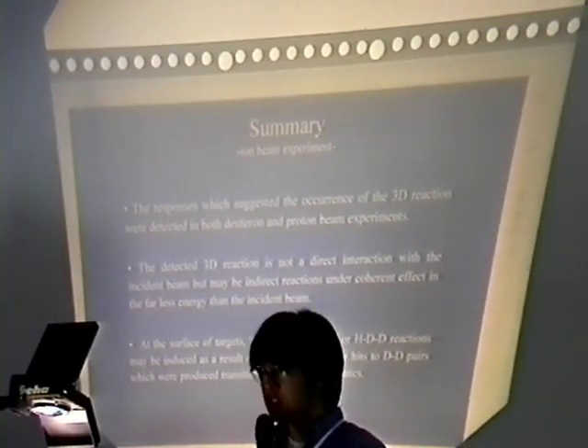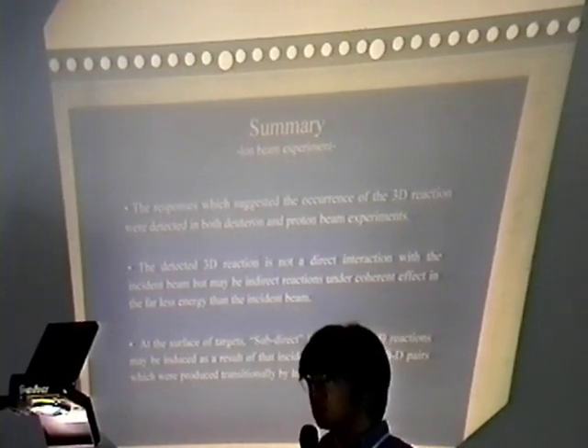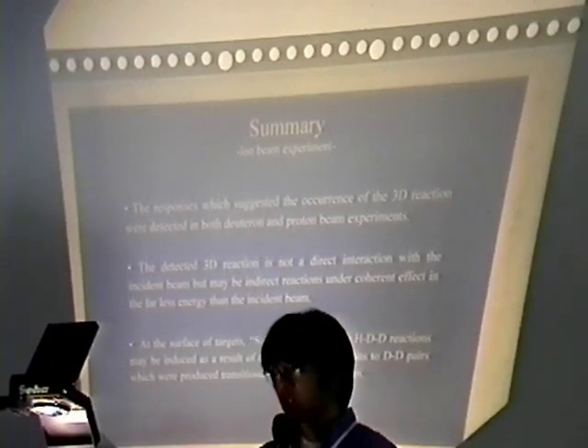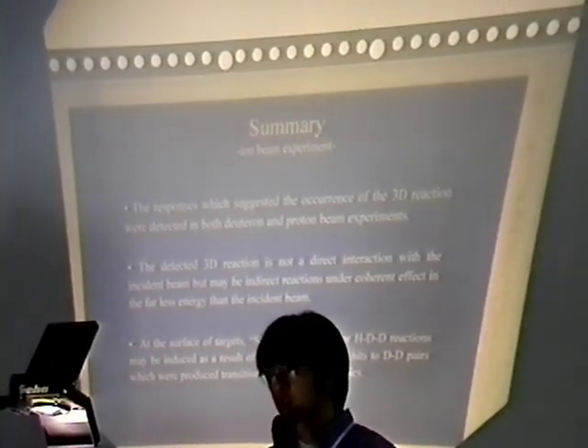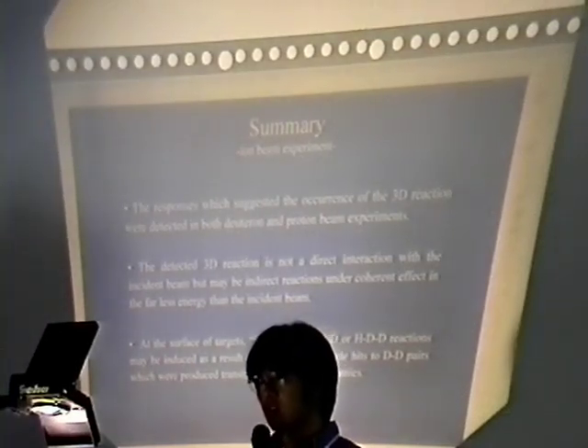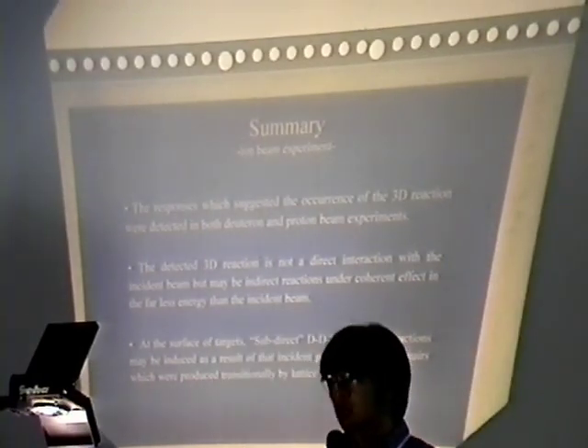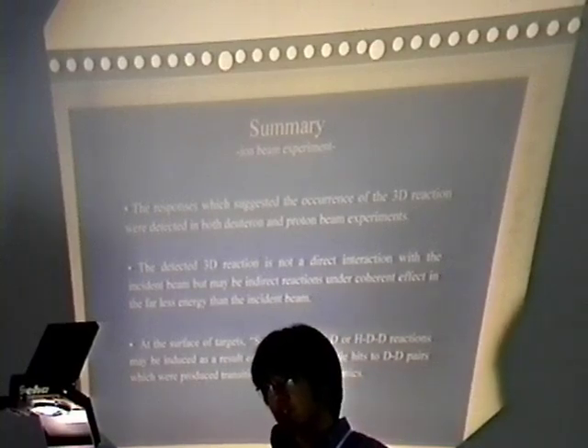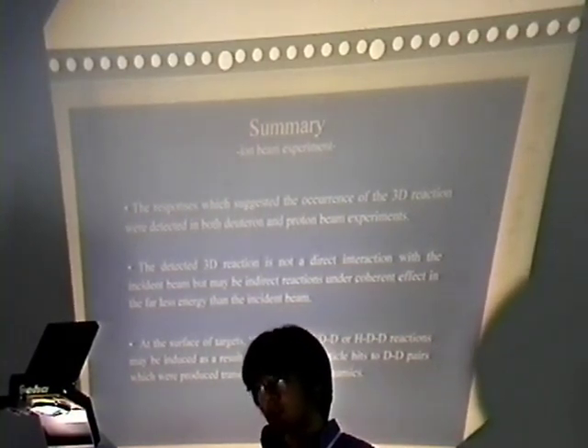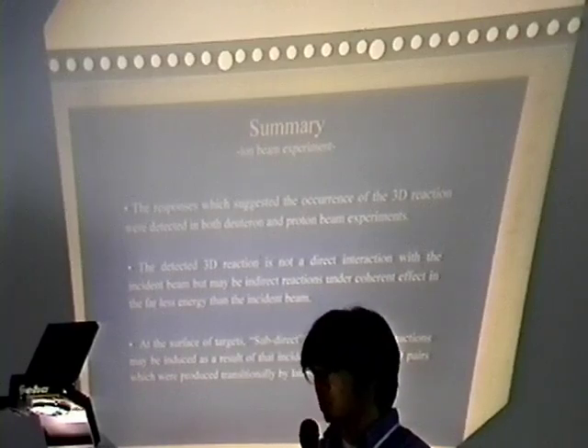Summary of the ion beam experiment. The responses which suggested the occurrence of the 3D reaction were detected in both deuteron and proton beam experiments. The detected 3D reaction is not a direct interaction with the incident beam, but maybe indirect reactions and a coherent effect at far lower energy than the incident beam. At the surface of the target, sub-direct DDD or HDD reactions may be induced as a result of the incident particle hitting DD pairs. DD pairs were produced transitionally by lattice dynamics.